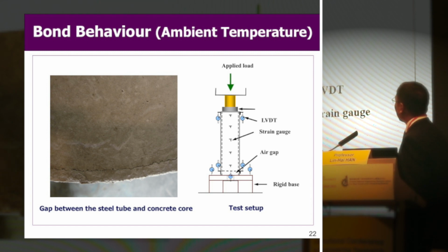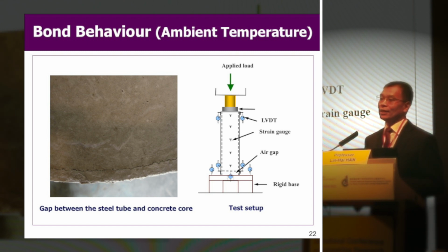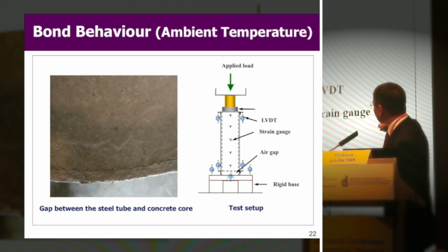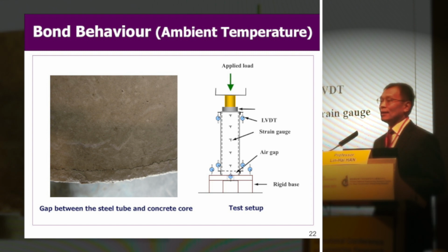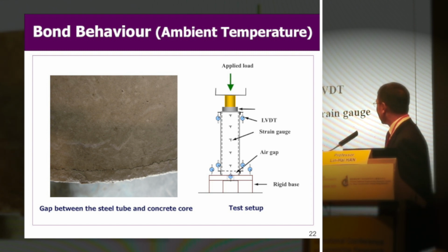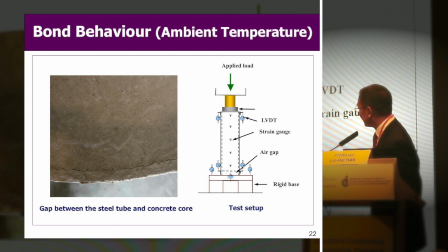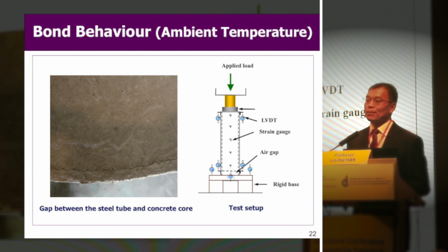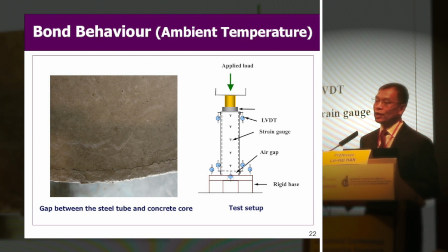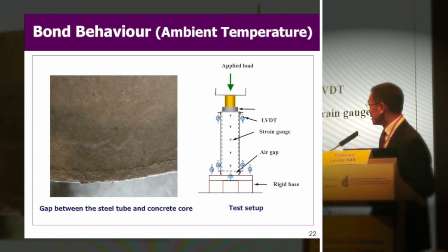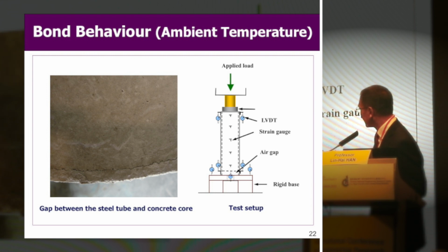So we have a type of push-out test. You can see a spacing here, a gap. We apply the load exactly on the core concrete only, to push the core concrete and check the slip at the boundary of the steel tube and the core concrete. Actually, before the test, we can observe there is some separation caused by the shrinkage of the concrete. So it's a changeable separation.